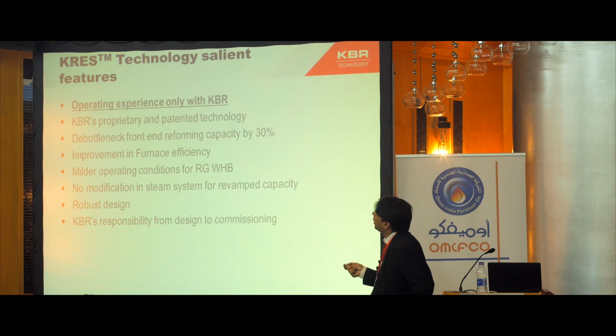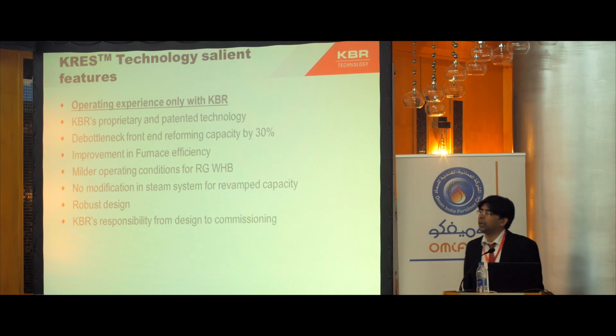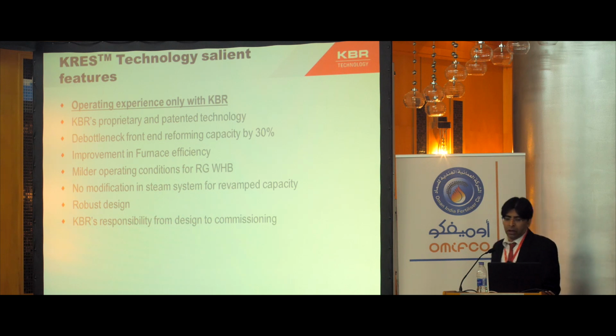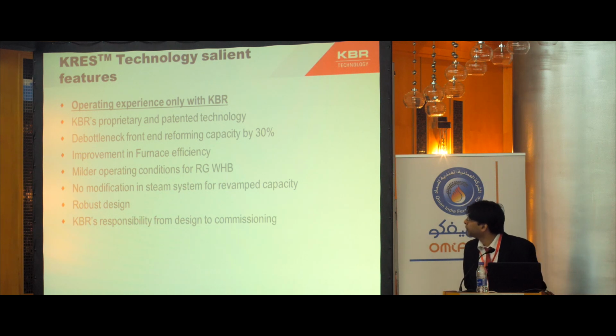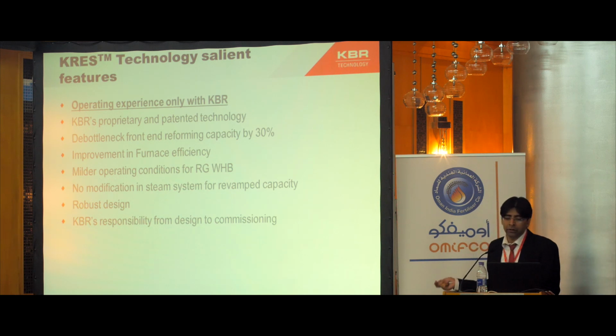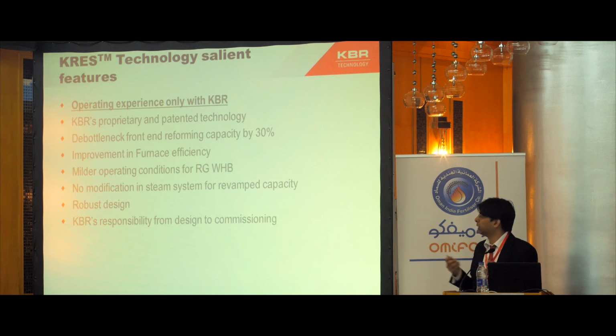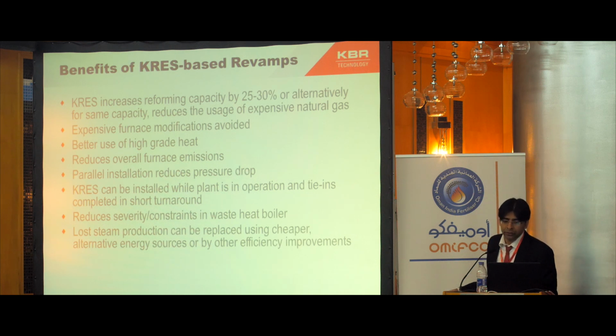It's worth noting that the operating experience is only with KBR. It's a KBR proprietary and patented technology which debottlenecks front-end capacity by roughly 30%. It also leads to improvement in furnace efficiencies. There are milder operating conditions for the waste heat boiler. There is no modification in steam system required for the revamp capacity. It's a robust design, and KBR has done various projects where we have taken the responsibility from the design to the commissioning of this plant. KRES increases the reforming capacity by around 25 to 30%, or alternatively, at the same capacity, it reduces the natural gas usage. There are no expensive furnace modifications required if we use KRES for enhancement of capacity.